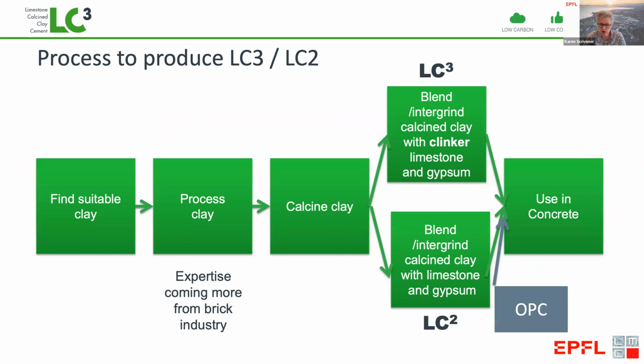Now, once you've got the clay, you have to process it and then calcine it. And then you can go in 2 directions. Either you can take the calcined clay and blend with the clinker and the limestone and the gypsum all together to give you what we call LC3, or you can produce a separate product, which is just the calcined clay, the limestone, and the gypsum, which is what we call LC2, and then blend that with OPC at the concrete level.